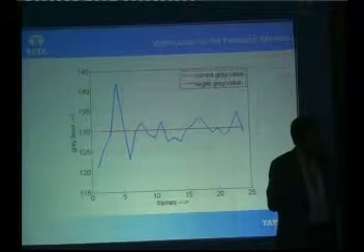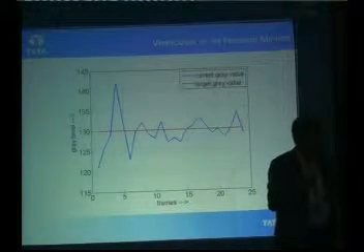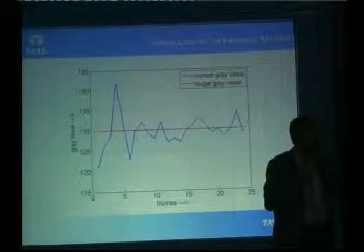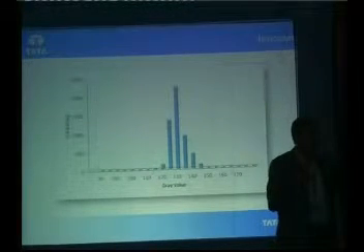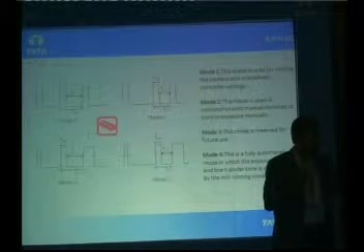We kept the target as 130, and we can see that over a period of 25 frames it is closely following the target gray value. Now the histogram is much more at its peak and the standard deviation is also very low. It is mostly concentrated at 130.